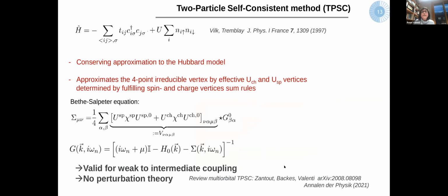So what we did here is to consider a different approach to calculate the self-energy that includes also a momentum dependence, not only a frequency dependence. This is the two-particle self-consistent method, which was initially introduced for the one-band Hubbard model by Vilk and Tremblay. The idea of this method is to start by analyzing two-particle correlations and doing some approximations to them. These approximations are done by fulfilling different types of sum rules. And at the end of the day, by doing this type of approximation, which is valid for weak to intermediate coupling, one can obtain momentum and frequency dependent self-energies.